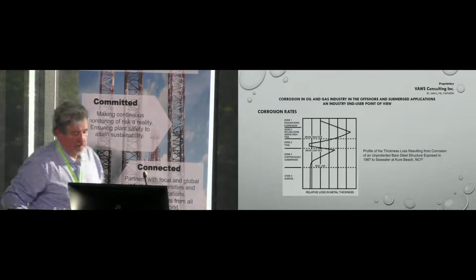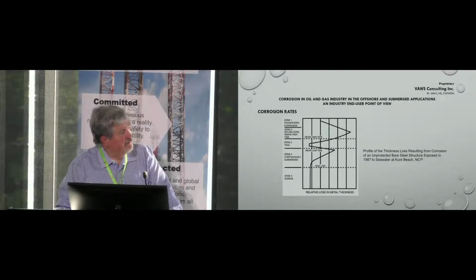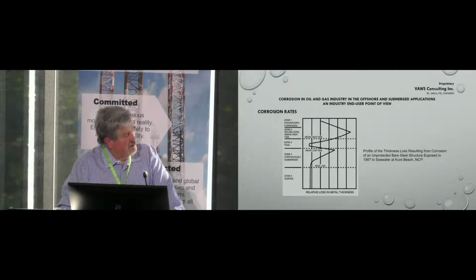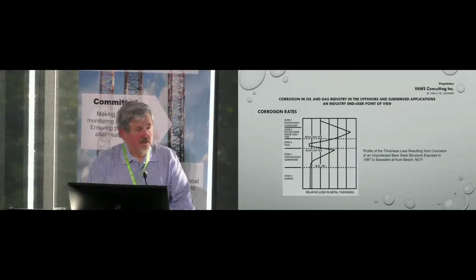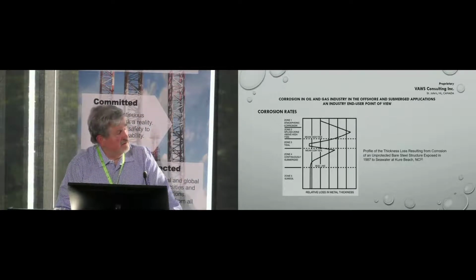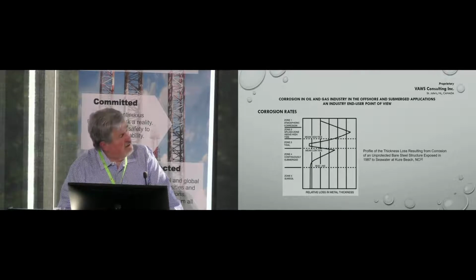This diagram shows the corrosion profile on the piling. And you can see that the section which is in the ground, which is the bottom section, has very little corrosion because there is no oxygen, and also there are elements which are buffering corrosion. As you go from the bottom, from the mud line to the surface, the corrosion increases. And then it goes back to low corrosion in the tidal zone. And in the splash zone, the corrosion is the highest it can be. This is because of the complete replenishment of the environment and the wave action of the seawater.